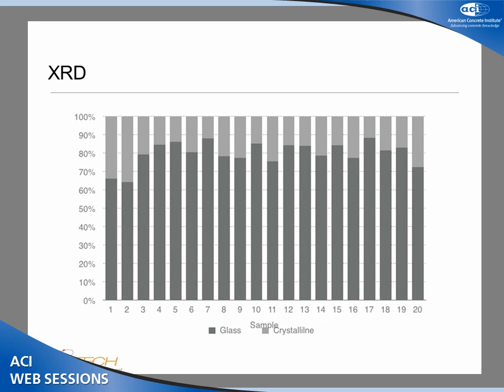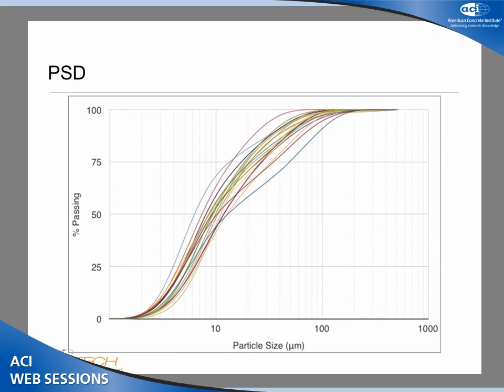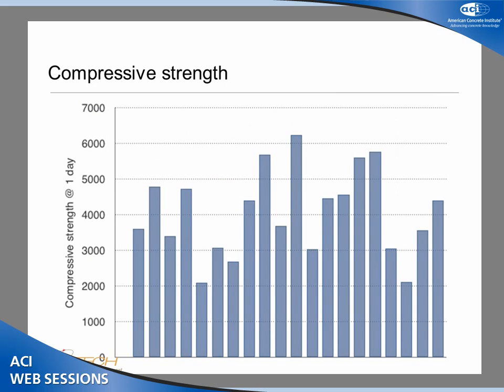That's the crystallographic characteristics. As you can see, the amorphous content ranged from around 65% to almost 90%. I don't have here the crystalline phases because, as I said, they can be considered relatively inert. That's the particle size distribution. Also, just to show you that they were pretty close together. There wasn't any big differences in the physical characteristics of the fly ashes. But here, as you can see, the differences in compressive strengths were huge, from 2,000 to 6,000 psi. So that's a big difference for such a short range in variability in the chemical composition.